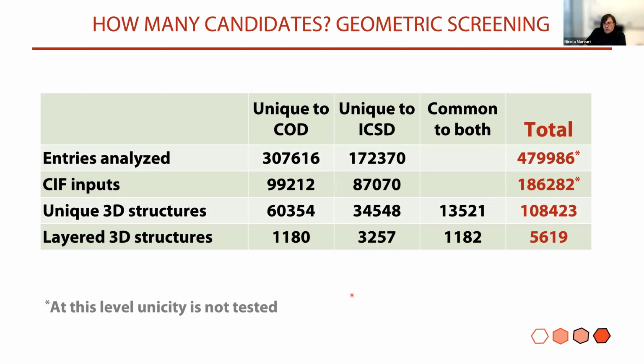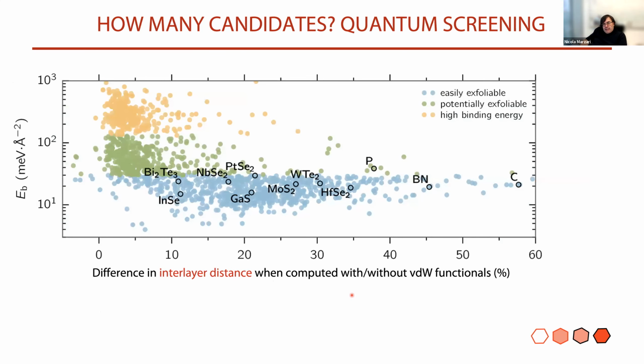So in this project, we started with roughly 500,000 inorganic materials. A lot of them might be disordered, amorphous systems, have a fractional occupation and so on. So we had 180,000 stoichiometric materials, of which at the time we worked with 2 databases, 108,000 were unique, 5,600 look layered, and on those we ran roughly 500,000 quantum mechanical calculations. So this is also interesting. I mean, the CPU costs of these projects were $40,000. So you can say it's a little or a lot depending on your perspective. But this is what we found.